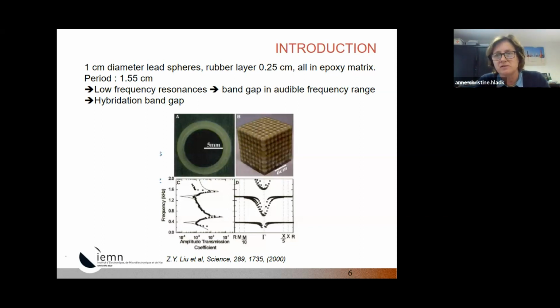This is the case for the famous paper from Ping Sheng with lead spheres, 1 centimeter in diameter, with a rubber layer, all in epoxy. And you have at low frequency a gap, a hybridation band gap. And so you can have attenuation even for small thickness.